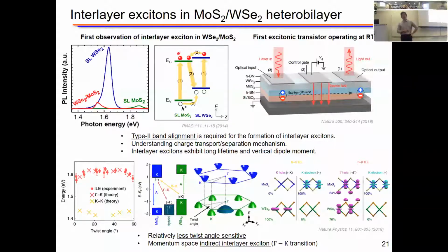Another interesting characteristic of this platform is that we can observe momentum-space indirect interlayer excitons, which means there's an optical transition between the gamma and K valleys because of the band hybridization at the gamma point. To give a little more explanation, the optical transition is allowed in the K-gamma valley transition because of the band hybridization, as opposed to K-K valley, where the dipole matrix element is strongly suppressed between the unlike states.